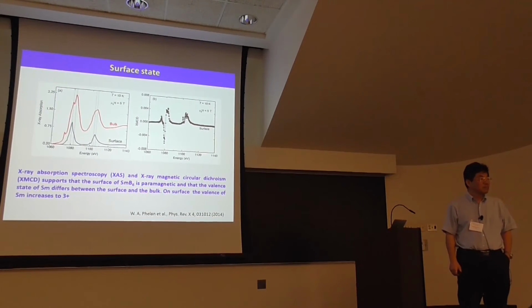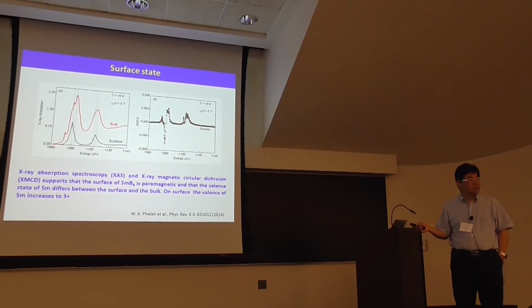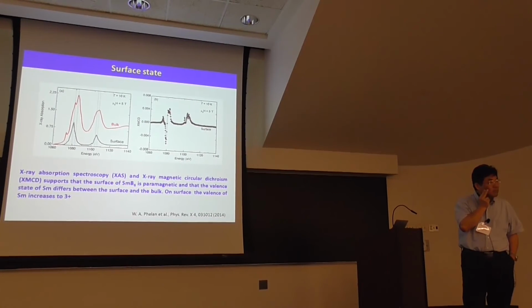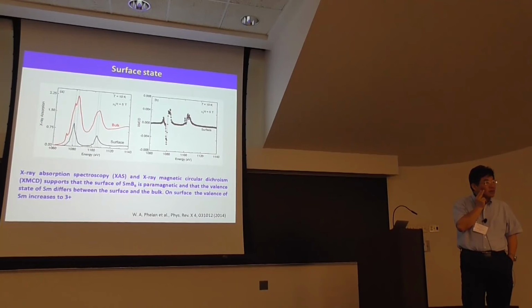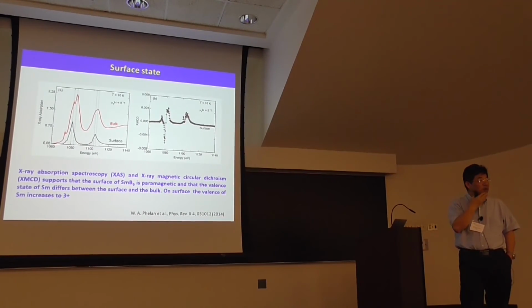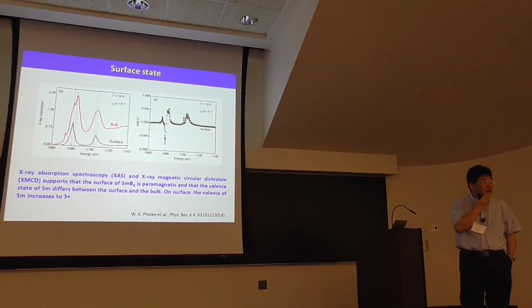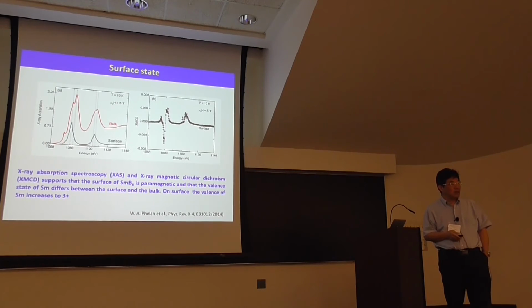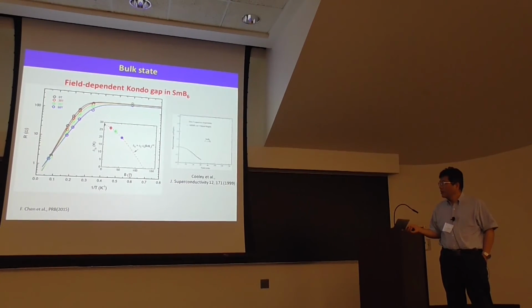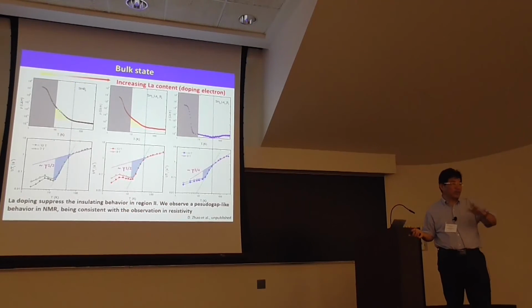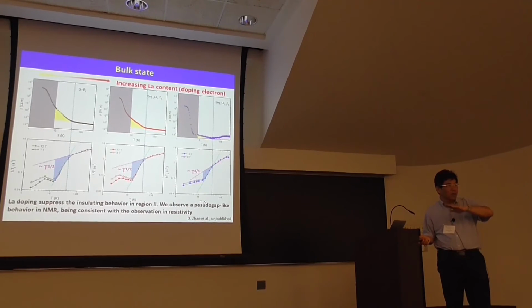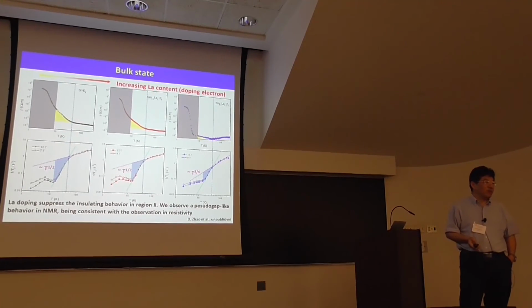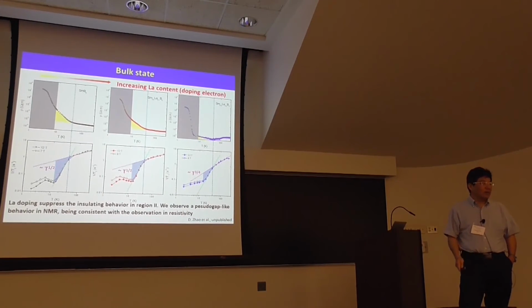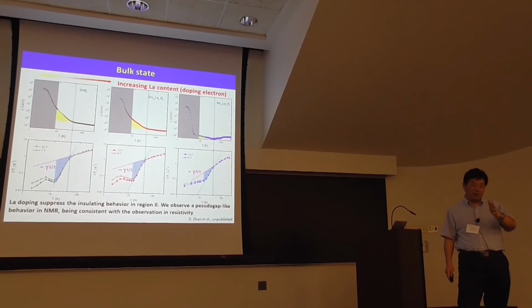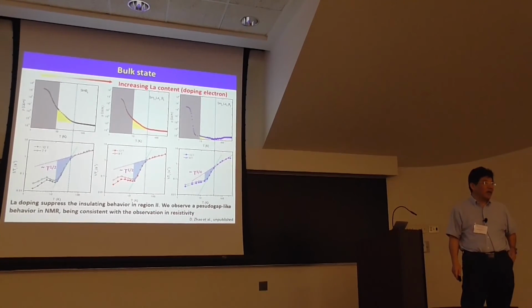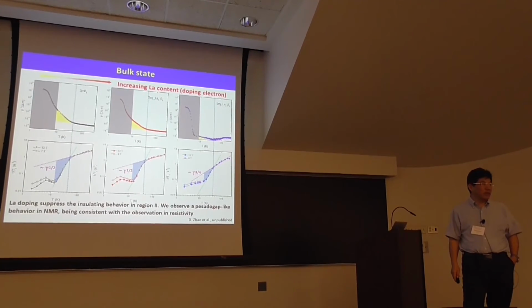For the paramagnetism and ytterbium defects, it was reported 10 years ago that paramagnetism began to appear. You mean a few years ago, some people have reported? 2007, a Japanese group. Okay, thanks. Also we do the NMR data. The NMR data shows that 1/T1 is different from the proportion, different from the behavior, and this is maybe a free local moment, some phase, magnetic order. I just show that. Thank you.